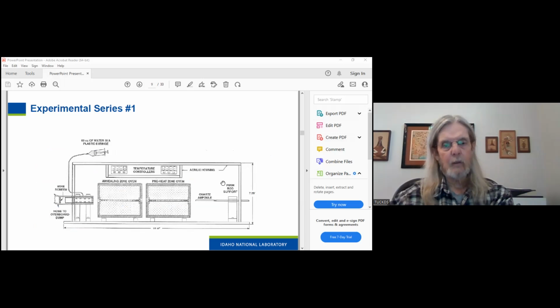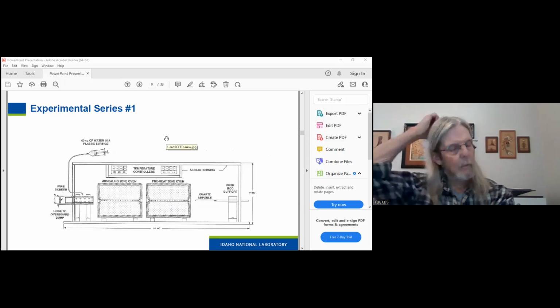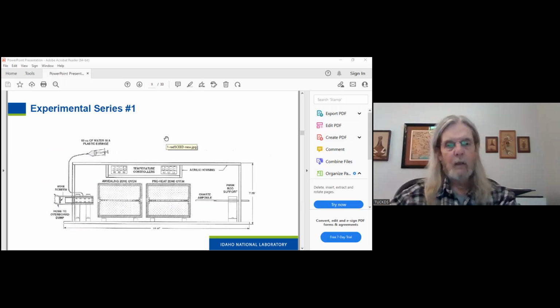And this is a little experiment I did. It was very inexpensive that I flew on the KC-135. And it consists of a push rod where you mount your quartz ampule with a fiber and a preheat zone oven. And what I'd do is I'd push the fiber in there before we got to the low gravity portion